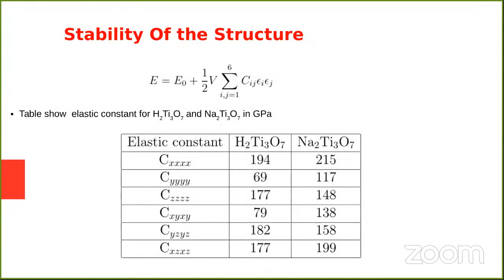And also we check the stability of this structure by applying strain to the unit cell. And then we calculate the total energy. This data was fitted by using a quadratic polynomial, and then the relevant elastic constants were extracted from the coefficients of the quadratic term in the equation. And here we tabulate all the elastic constants for all the cells for hydrogen titanate and for sodium titanate, in units of gigapascal.